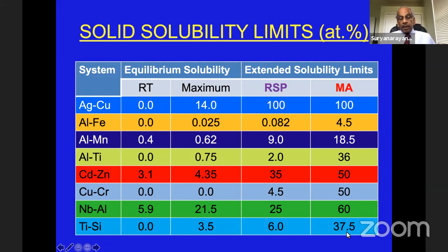You can see in some cases, instead of 14% maximum solubility of copper in silver, you can go to 100%. That means silver and copper can be made an isomorphous system. In fact, if you look at the Hume-Rothery rules for solid solution formation, silver and copper are supposed to be forming the isomorphous system, but it forms a eutectic system. And if somebody was asking, why is it a eutectic? Oh, it's an exception. That's how people use it to have a hand waving argument. But by non-equilibrium methods, you're able to increase the solubility of copper in silver from 14 to 100%, by both the techniques. Whereas in other systems, you do not expect 100% solid solubility, but only a small increase.